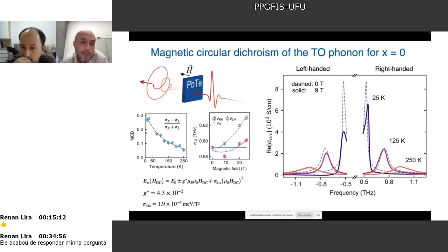And if we plot this MCD as a function of temperature, you can see that it increases with a decrease in temperature, as we can see here. For high temperature it is more or less the same. For low temperature there is a large difference. So more or less 30% MCD we can obtain for lead telluride.